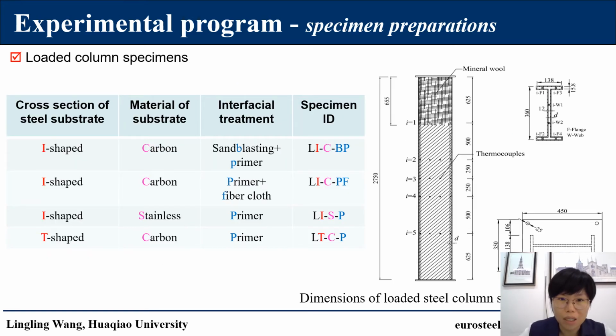Loaded column specimens consist of 3 I-shaped specimens and 1 T-shaped specimen. 1 loaded column used stainless steel, the other 3 used low-carbon steel. 1 of the 2 I-shaped carbon steel columns was sandblasted before applying a primer. 1 test specimen had 1 layer of carbon fiber cloth placed on the surface after the application of the primer but before application of intumescent coating.